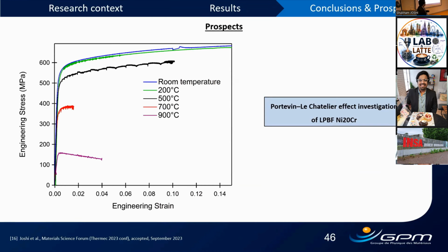Finally, we did some high temperature tests, and the reason I added this in prospects is that nickel 20 chromium has a propensity towards forming short range order at close to 550 degrees Celsius. And if we look at the LPBF microstructure, it is already complex, and now if we have short range order, it could be even more complex. So understanding that is still necessary for successful application of nickel 20 chromium. And if we look at the engineering stress strain curve at 500 degrees Celsius, the test temperature, we clearly see the dynamic strain aging.